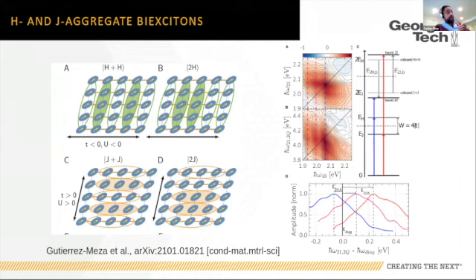I'll also mention that this is at 5 Kelvin. At room temperature, the story is the same. It doesn't change. Of course, the spectra are a little bit sharper, nicer at 5 Kelvin. So in these spectra, there is no population signature of bimolecular annihilation. I'll also mention that the fluence here is of the order of, I think, something like 30 nanojoules per centimeter squared. If we do a pump-probe experiment at this fluence, it would be relatively minimal. We can go to higher fluence, and we see that. In fact, that contaminates the line shape in ways that add an additional incoherent contribution. But the point is that there is also a way, through the line shape, to tell whether there are bimolecular annihilation effects. And at this point, they are not dominant, but we still, of course, see the exciton-biexciton correlations.